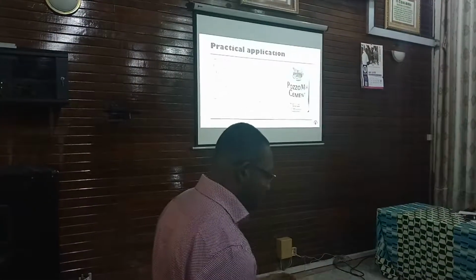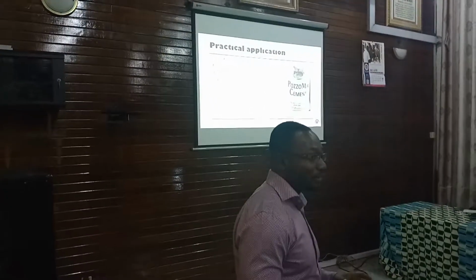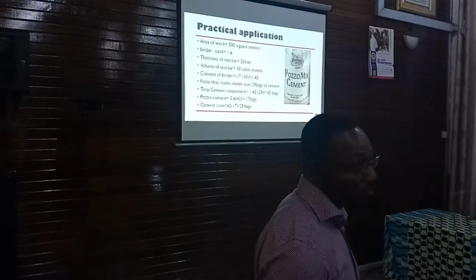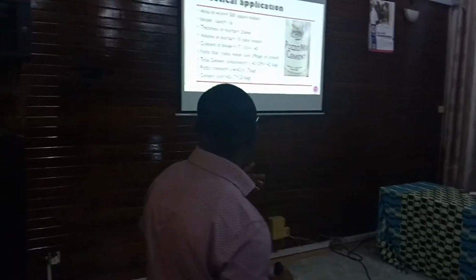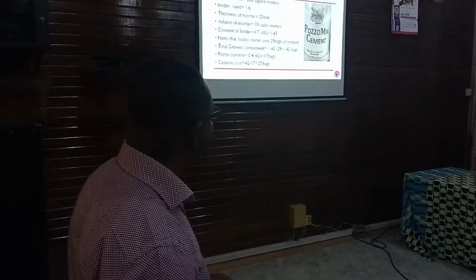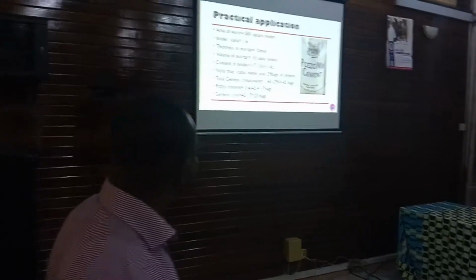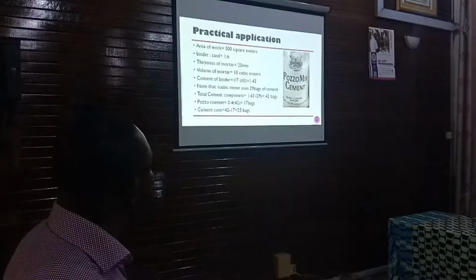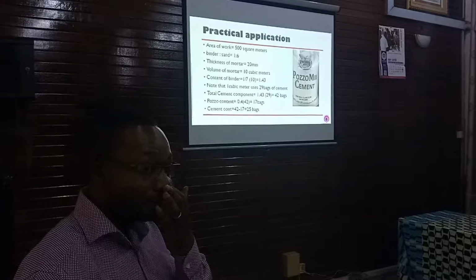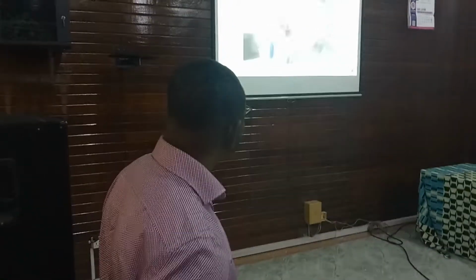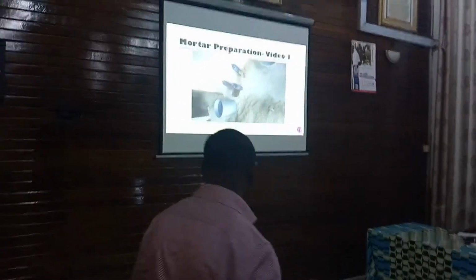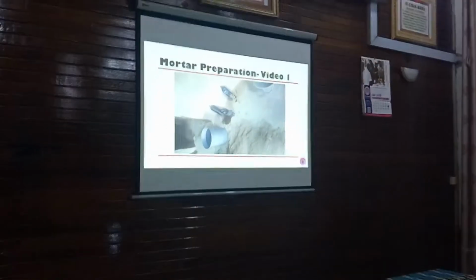So in the field, it is known that 29 bags of cement can produce 1 meter cube of mortar. So from these things and the calculations, you can estimate the content of pozzolan, which is about 40%, to be 17 bags, and then the cement content 25 bags for the work of 500 square meters. So that was the basis, and that was how the calculation was done. Okay, so this is a video that we can appreciate from the field.